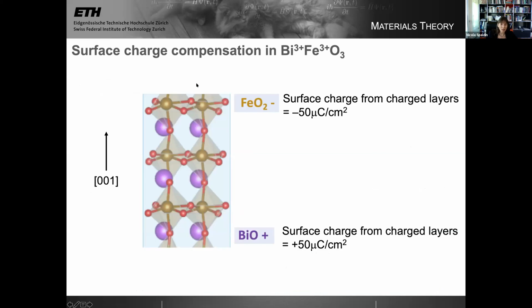Okay, so here's another cartoon. Here's my slab of bismuth ferrite. I've put an FeO2 surface at the top, and so I have a surface charge from the charged layers of minus 50 microcoulombs per square centimeter. I put a bismuth oxygen layer at the bottom, so I have a surface charge coming from this charged layer of plus 50 microcoulombs per square centimeter. Then in addition, in ferroelectric bismuth ferrite, in its polar ferroelectric state, I have a spontaneous polarization in addition to this, whose size is 50 microcoulombs per square centimeter.